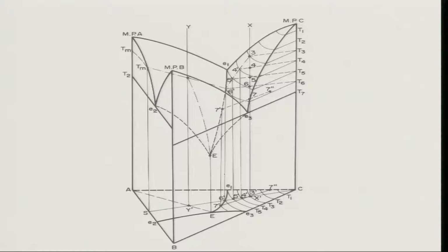So, now this is what we are going to spend a lot of time on, how the solidification will happen. In this system, where there is no terminal solution, obviously there are many alloys which will undergo Ternary eutectic reactions, not only the alloy which has exactly the Ternary eutectic composition corresponding to E, but a composition corresponding to X, Y, even compositions corresponding to X and Y, they will all actually, because they are falling on the regions of A plus liquid or B plus liquid or C plus liquid.